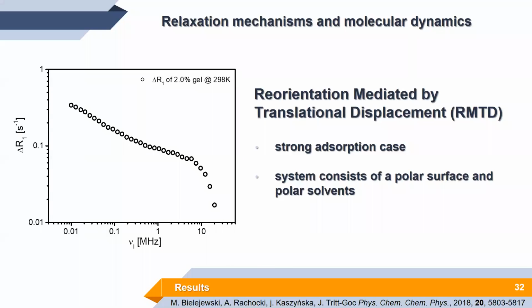So now we turn ourselves to reorientation mediated by translational displacement, the RMTD model, which I believe is familiar to you. It is a model which assumes that we have strong adsorptions at the surface of the, in our case, gel matrix. And the adsorbent molecules are the solvent or the ions that can stick to the surface of the gel matrix. Of course, this is possible when we have a strong polar system in terms of the surface of the gel matrix and in terms of course of the diffusing molecules.